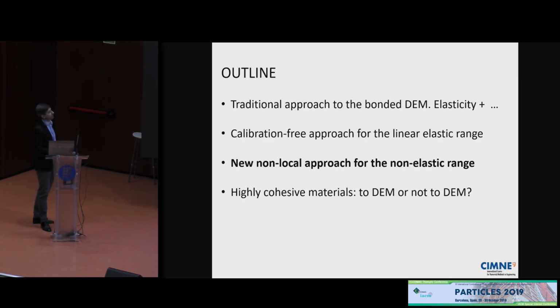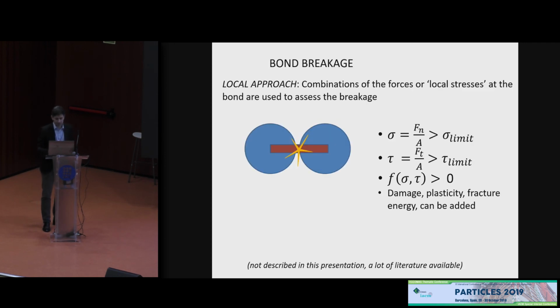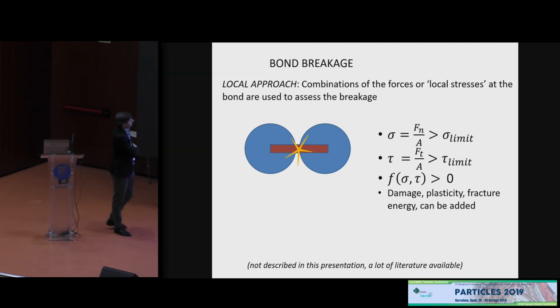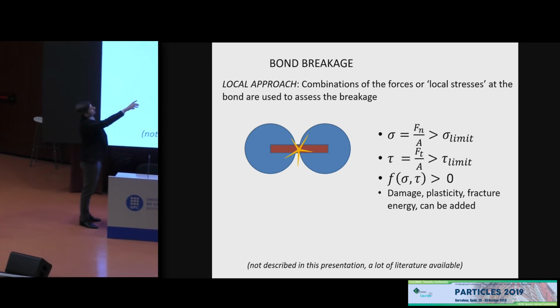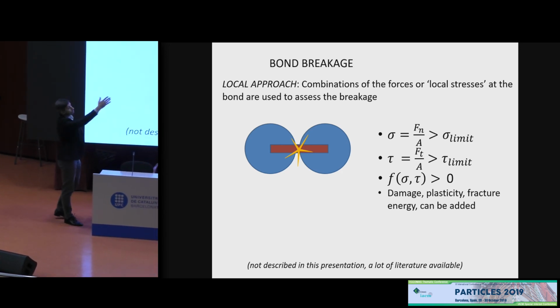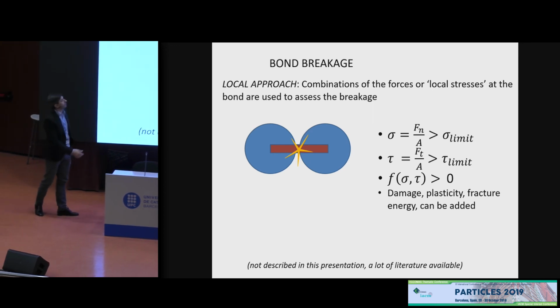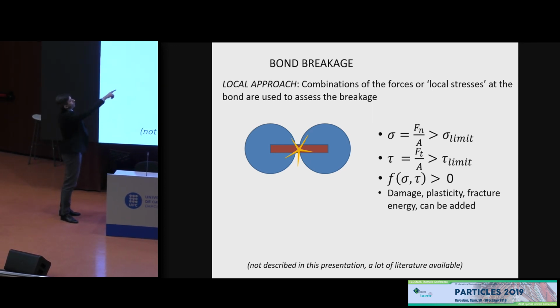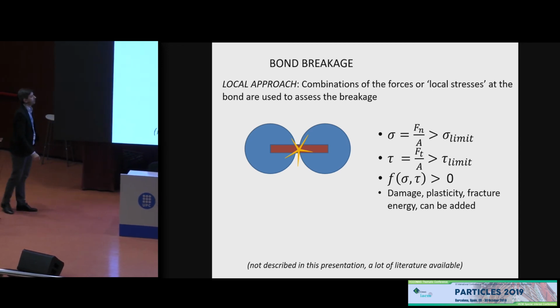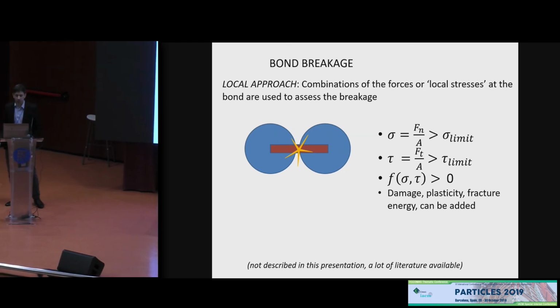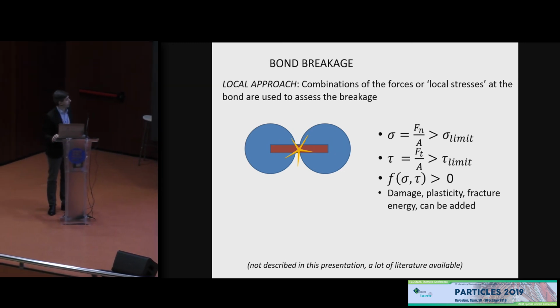Now, the second idea is about the non-elastic range. Usually, for breaking the bonds, we use the local approach. That means combinations of the forces or local stresses at the bond, and you compare them with the limit. For example, you compare the normal stress to a limit stress, and if that's bigger, then you break the bond, or a tangential stress, or a combination of both, and you can add damage, plasticity, fracture energy. Those things can be added to the bond, and that's pretty useful.